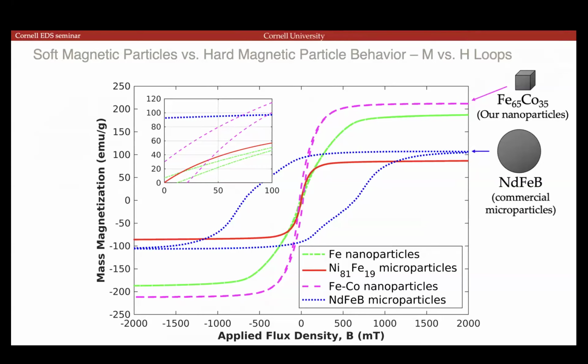curious at some point. Yeah, the difference between soft or hard, the hysteresis all comes down to what I've been describing as coercivity. So what we've been trying to do is actually the opposite of what you're trying to do. We've been trying to increase the coercivity so that we can increase the width of this curve and therefore increase the remnants. But to first order, it comes down to coercivity, unless you can shape it so that it has high coercivity but then drops really rapidly after that. Right, because from a loss perspective, I don't care whether it's high coercivity or not, but I do want the area to be small. So the blue curve would be fine, but then the slope is too low. So I'd rather, once it goes negative, just flips.